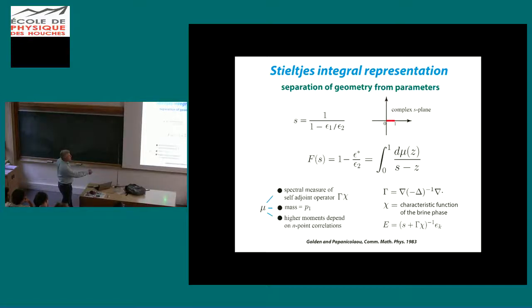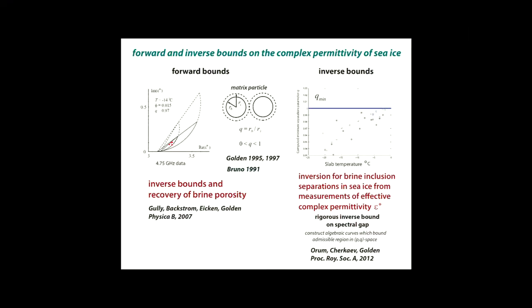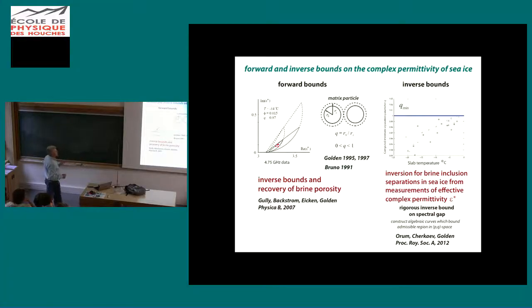The mass of the measure is the volume fraction of the brine, and the higher moments depend on n-point correlation functions. And what really makes the method go is this very beautiful resolvent representation for the local field in the problem, in this case the electric field, in terms of that operator. So everything can be expressed in terms of this basic operator. We've done a lot of work on using that integral representation to get rigorous bounds in the complex plane on the effective complex permittivity. Here are some very tight bounds under this so-called matrix particle assumption, where you assume that the brine is really in separated inclusions. And these are inversions here, where we can actually see how the brine inclusions literally start to coalesce and get closer and closer as the temperature is increasing. But again, this is all done electromagnetically.